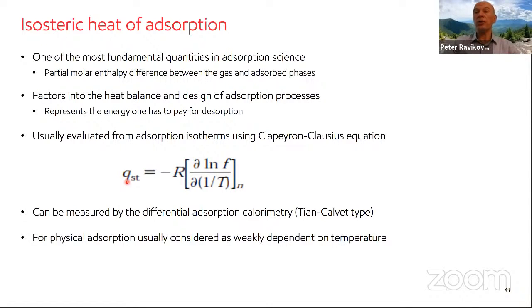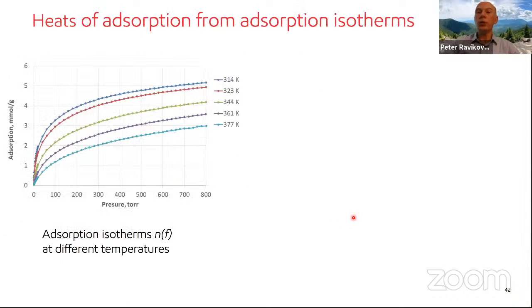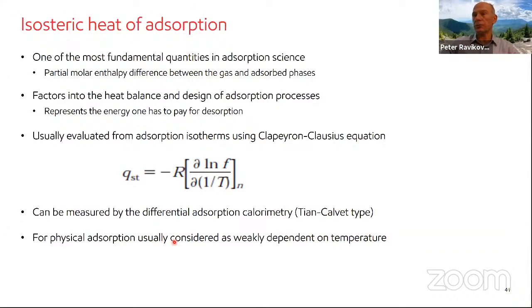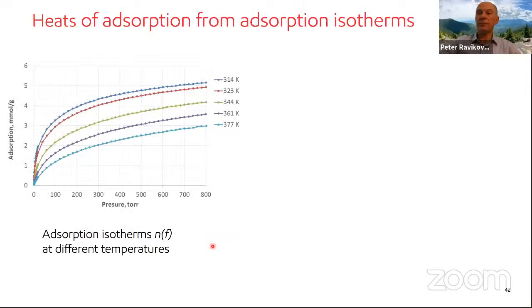You can also measure it in a differential adsorption calorimetry of Tian-Calvet type. And what is important is that for physical adsorption, which we typically deal with in porous materials, this heat of adsorption is a weak function of temperature. So let me illustrate this. This is CO2 on 13X zeolite. Isotherms very carefully measured within the range of ambient and a little higher than ambient temperatures.